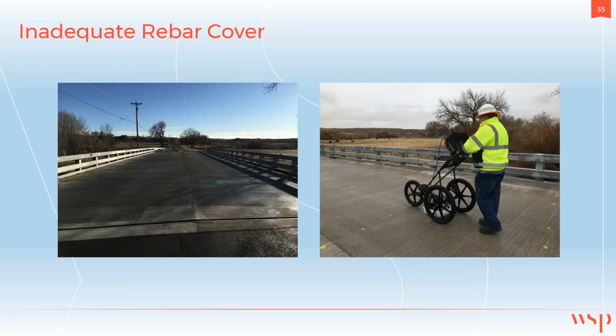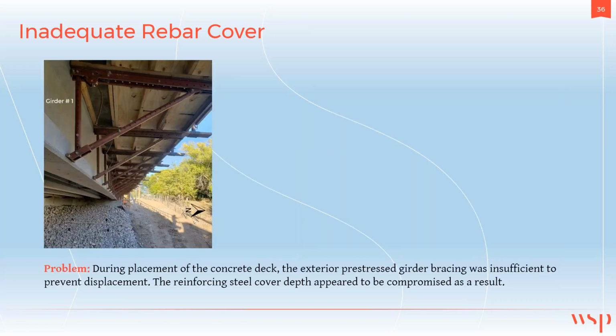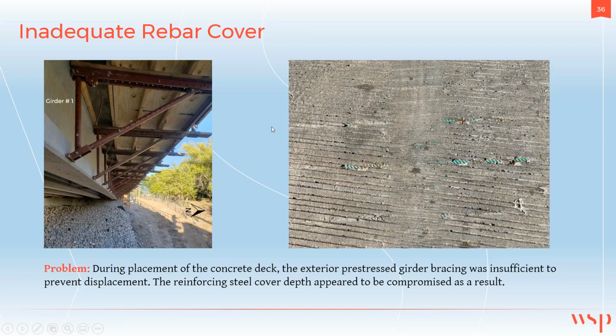This is a newly constructed bridge. The bracing for the north exterior girder was insufficient to prevent displacement during the pour, and as a result, the concrete cover on the north half of the deck was compromised, as you can see in these pictures.